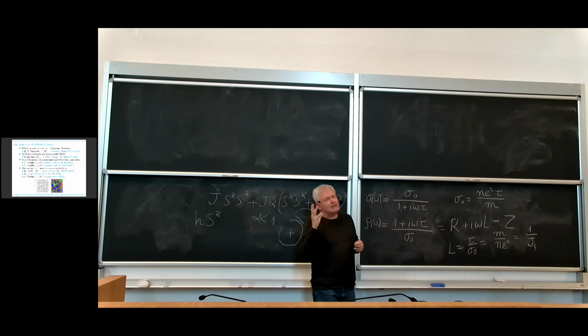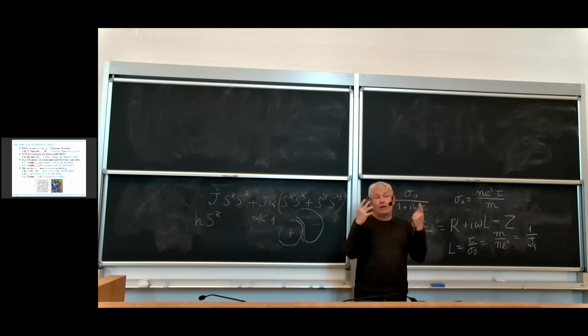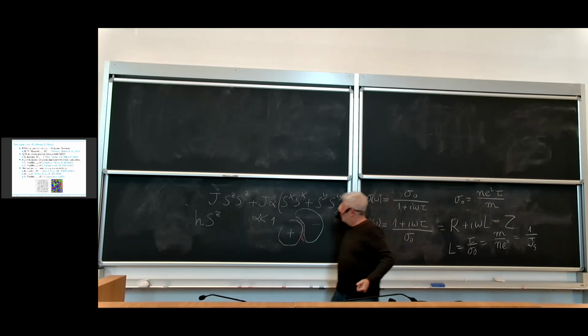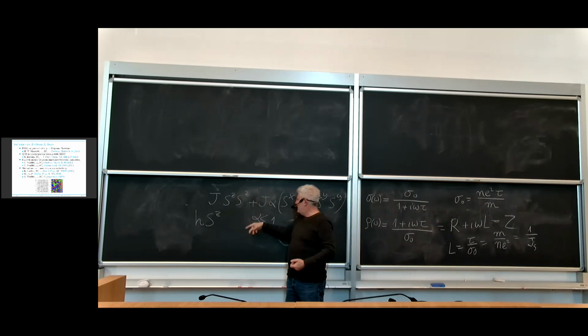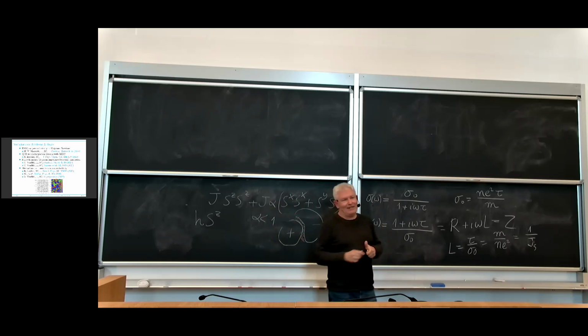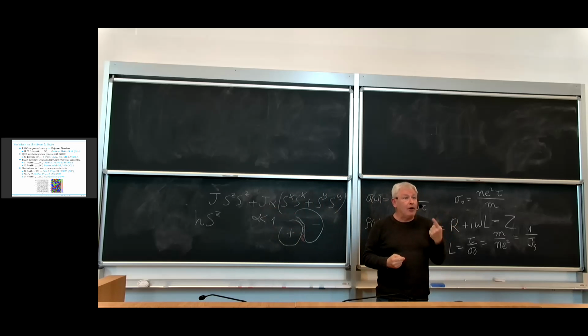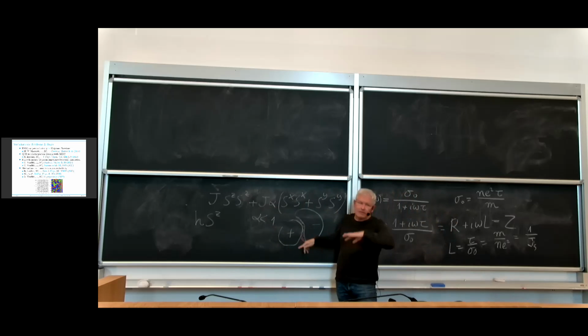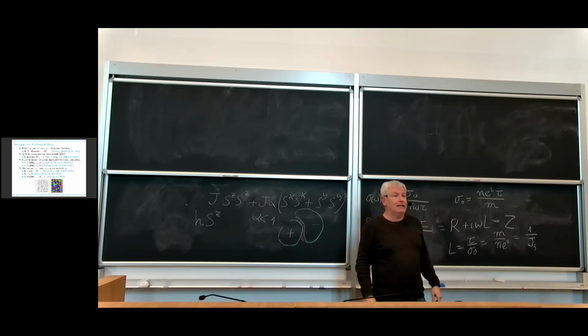With Ising spin, of course, you must be not too far from the symmetric point. So this is still a very strange model because you are saying that the two ground states are very close in energy. So it's not so difficult to tilt the balance. Of course, if I go deep inside the Ising phase, so if I take a very small alpha, then there is no way that the system can develop a superfluid stiffness. Of course, you will have domains, but no superconductivity around.